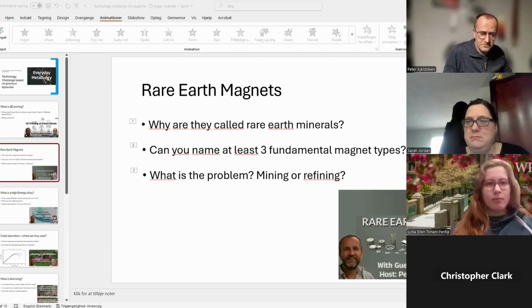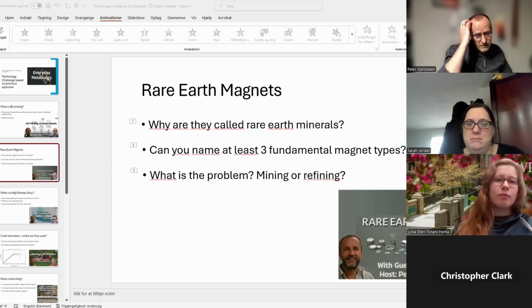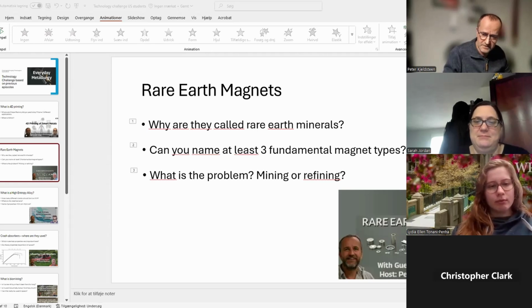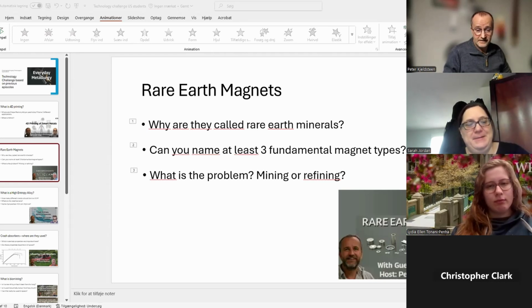But recently, there are also magnet types like samarium cobalt. They are designed for high temperature applications. Today you can make samarium cobalt that can stay magnetic up to around 450 degrees C. And the latest, maybe not on the market today, is being developed by an American company named Niron. It's an iron nitride magnet, a magnet type without rare earth elements. So it is based on abundant materials. We're not depending on other countries or other regimes.